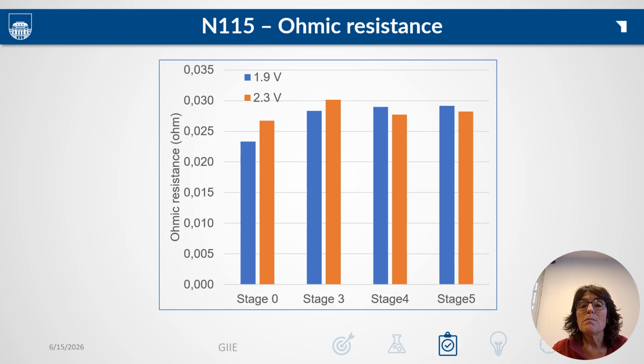And here is the most important point of comparison. When we measured fluoride in the effluent at the end of the Nafion 115 campaign, the result was below the detection limit. So even though this membrane is thinner, the iridium-ruthenium oxide anode suppresses the formation of reactive oxygen species and protects the polymer backbone from chemical attack.